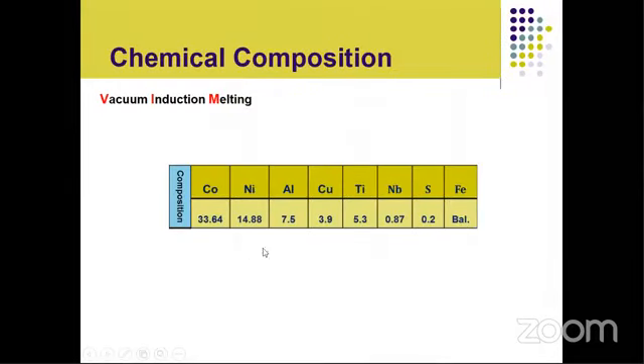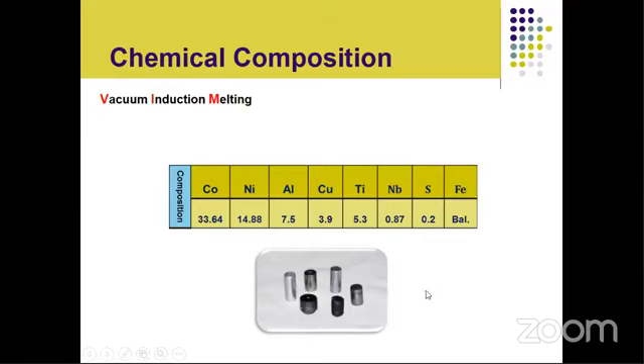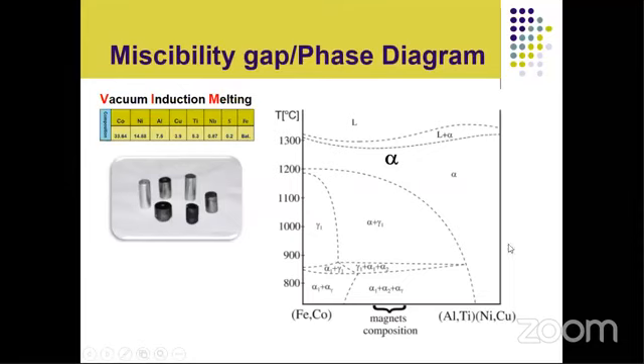So this was the composition of the alloy which we prepared by vacuum induction melting. Iron was the balance; the rest of the composition is written here. The composition was determined by the ICP technique. These are the rods which were developed by vacuum induction melting. So this is the phase diagram of our system. On the left side we have iron and cobalt, and on the right side we have nickel and copper, which also include aluminum and titanium and sulfur. Here we have the composition which we have prepared.